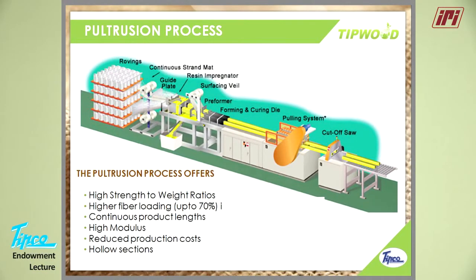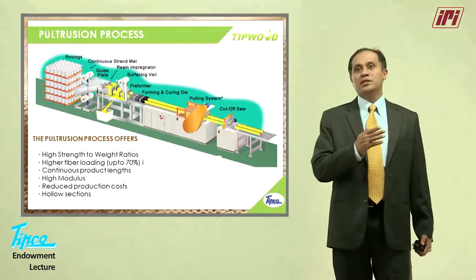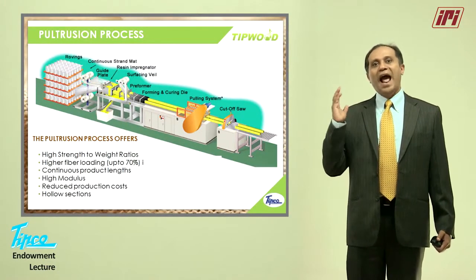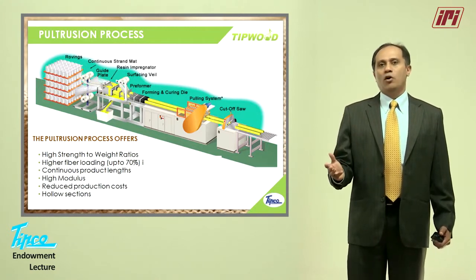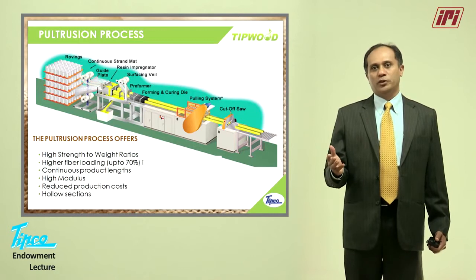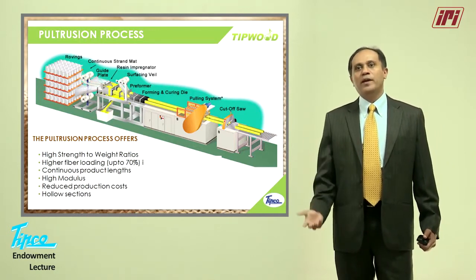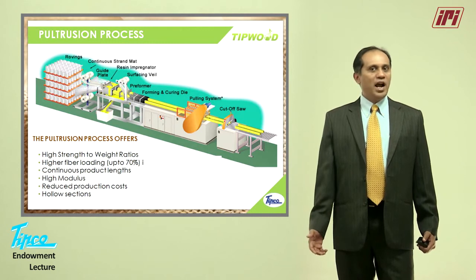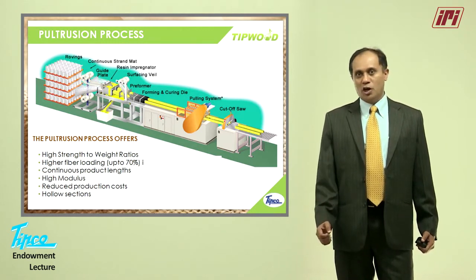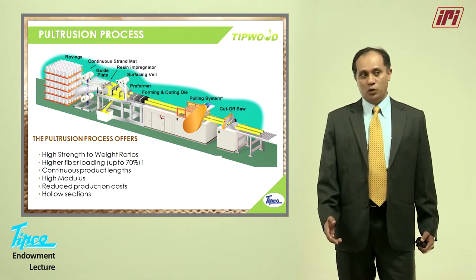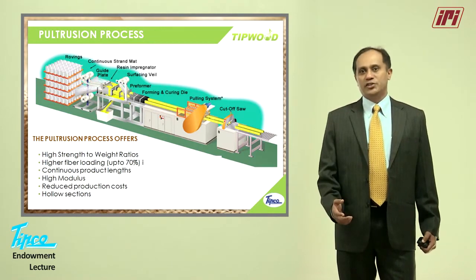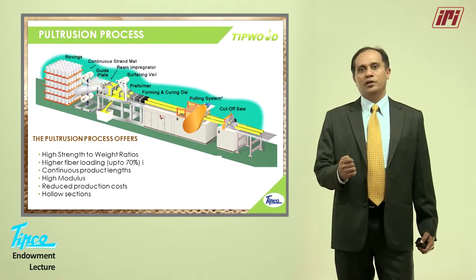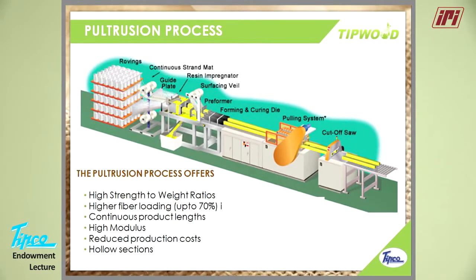It is a process like extrusion. It offers high strength to weight ratios, high fiber loadings, almost up to 70%. It's a continuous product length. That means technically you can make this product as long as you want, or in more practical terms, as long as you can transport it. So if you can put it on a 40-foot trailer, you can make a 40-foot section. It's got very high modulus, reduced production costs because the energy requirement for this is very low, and you can make hollow sections, which is a new thing in wood replacement. In wood, to make a hollow section is very costly, but in our technology it is very easy.